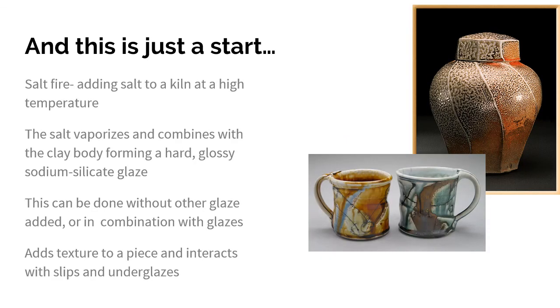A salt firing kiln is also a really common technique. So in a salt fire, it's typically with a gas kiln, and you set the kiln at a really high temperature and you literally just pour in table salt. You can also soda fire with some other materials. So when the salt is put into the kiln, it vaporizes, it turns into a gas, and it combines with the clay body, forming this hard, glossy sodium silicate glaze. So you can actually put bisque-fired pieces into a salt kiln, and they will end up with shine and texture, even if there's no other glaze on it.